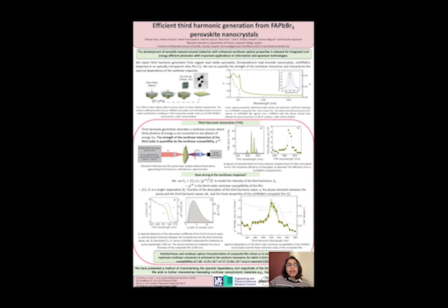In this poster, I am presenting the efficient third harmonic generation from organic halide perovskite nanocrystals, more specifically from formamidinium lead bromide nanocrystals dispersed in an optically transparent silica film. Easily integrable halide perovskite nanocrystals are exciting due to their stability, strong absorption above band gap, and a high dielectric constant which promotes strong nonlinear responses.